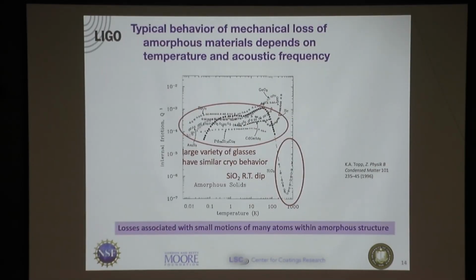This is a rather famous plot. This is a plot of the internal friction, the thing I've been telling you about. I'm showing it as 1 over Q. So it's the losses, 1 over the Q factor of the film, of a whole ton of materials on a log scale. This is log scale, that's log scale. A whole bunch of glasses, and they're all in this universal range. All these different materials. And in fact, this is an early plot. It's been extended. Everything has losses that are up in this range of 10 to the minus 3 to 10 to the minus 4. So this is referred to as the universal glassy range.